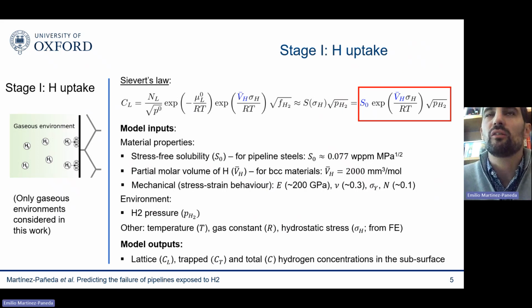But otherwise, it's pretty straightforward. But again, I must emphasize that this is not negligible, because normally we measure this solubility using a permeation experiment. And in a permeation experiment, of course, the tensile condition is an unloaded sample. So it's going to be very different to those ahead of cracks in a pipeline. So that's important. But we know what is the contribution of the hydrostatic stress, sigma H.